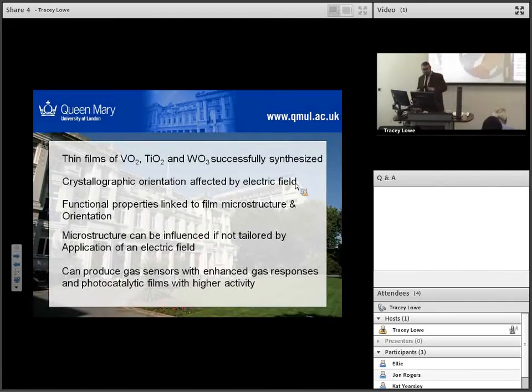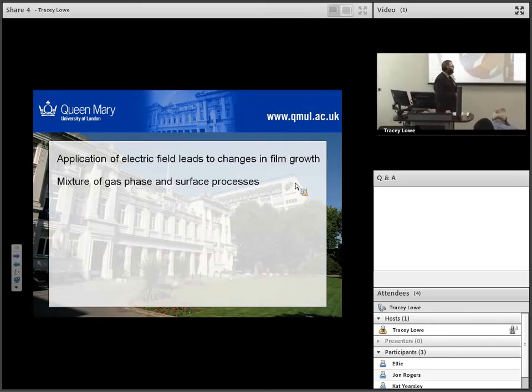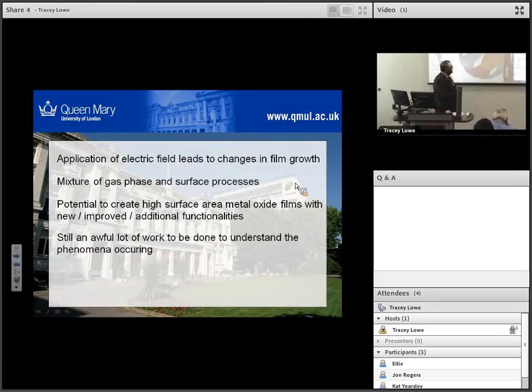We can make a bunch of these metal oxide films, we can change crystallographic orientation, and as the functional properties are linked to this microstructure and crystal structure, we can see different functional properties. We can tailor this microstructure to some extent. Just a couple of examples I've given you: we can make gas sensors with enhanced responses, photocatalytic films with apparently higher activity, and various other bits on supercapacitors and whatnot. I want to go through the photovoltaic stuff.